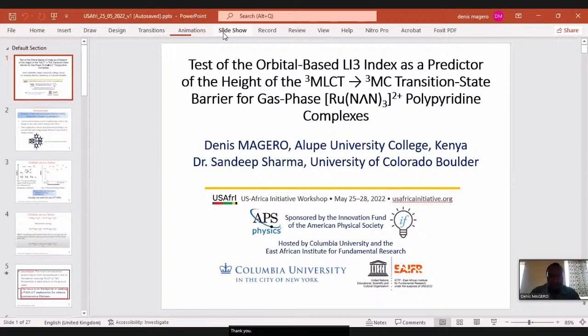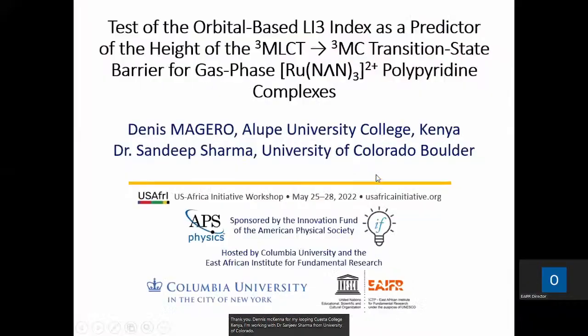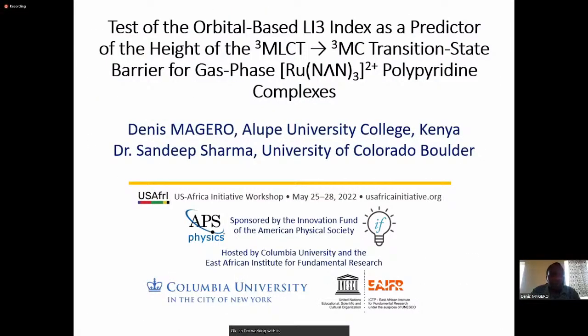I'm Dennis Magero from Alupe University College, Kenya. I'm working with Dr. Sandeep Sharma from the University of Colorado. Could you put it in slideshow mode? Recording in progress. So I'm working on the test of the orbital-based Li3 index as a predictor of the height of the triplet metal ligand charge transfer to the triplet metal-centered transition state barrier for the gas phase ruthenium polypyridine complexes.